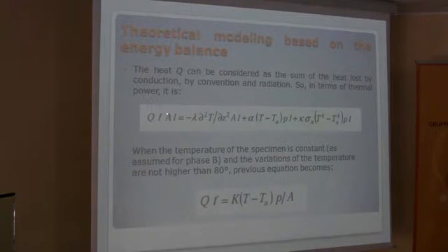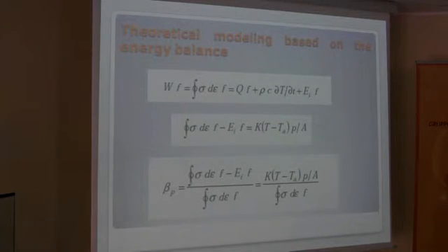multiplied by the frequency, and the power is in three parts linked to conduction, convection, and radiation. But at low temperature, the second one, convection, is predominant with respect to the others, which are negligible. And at the end, it is possible to give a simplification and correlate the plastic damping, which is the ratio between the energy loss and the energy applied to the specimen, directly with the temperature,